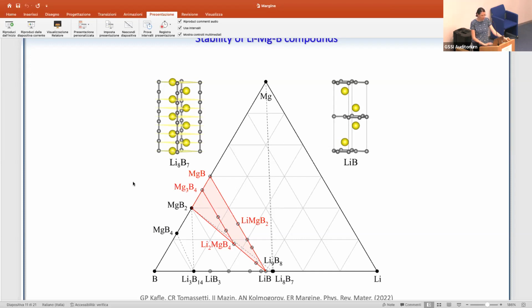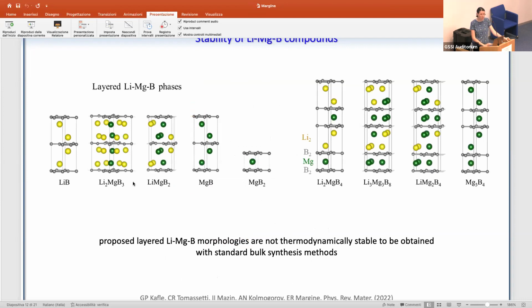Compared to the previous study by Alexei, in this latest study we have also looked at varying the composition by mixing the composition at the sites of the intercalant, mixing lithium and magnesium. And these are the proposed lithium magnesium boron morphologies. We have performed thermodynamic stability analysis at high temperature and pressure, and we found that all these systems are metastable and unlikely to be synthesized with a standard bulk synthesis method. On the other hand, being layered materials, it may be worth investigating the possibility of synthesizing them using deposition techniques.